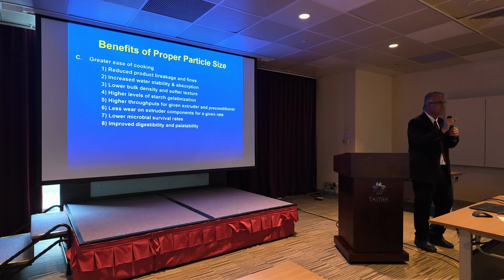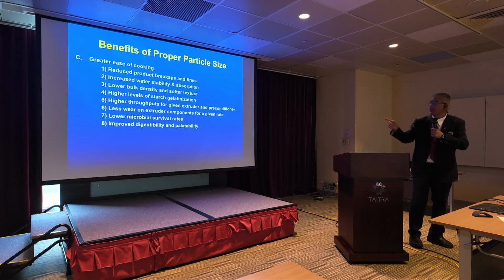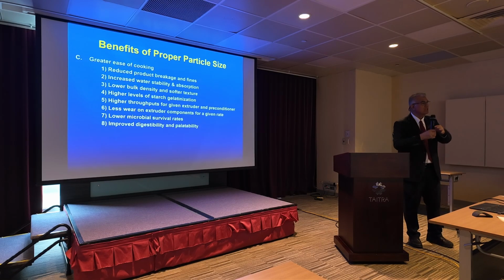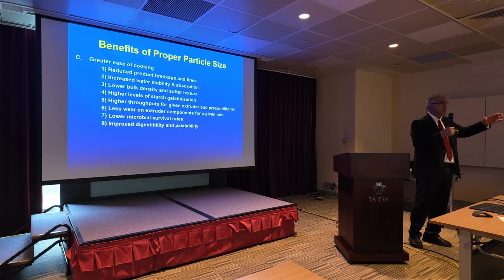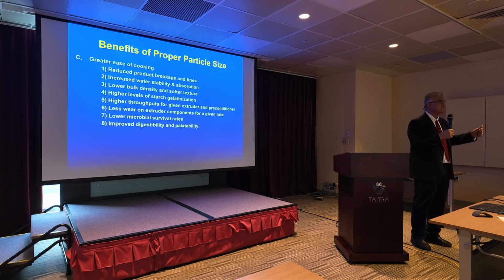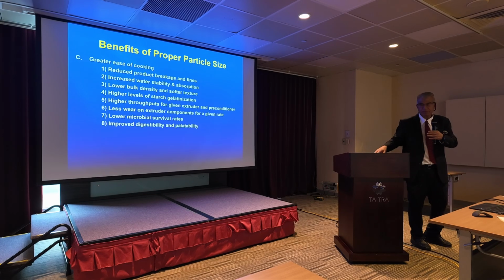it is still big pieces. Also, when you ship material from here to another place, roads are sometimes bumpy and you break a lot of fines, break the pellets into fines. How do you get the fines? Exactly where the big pieces are, not properly ground, that's the breaking point. That's where the pellet is going to break. Therefore, you have a lot of fines, a lot of breakage. You don't want that to happen.